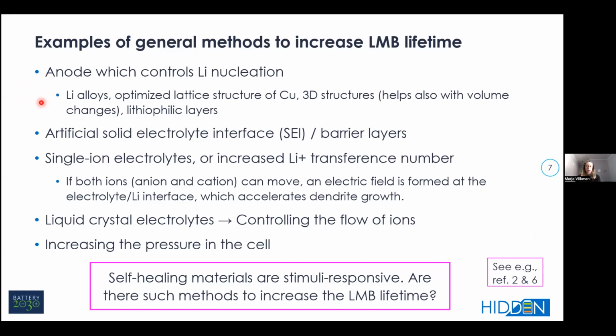So there can be different lithium alloys. We can also optimize the lattice structure of the copper current collector. Have some 3D structures in the anode or lithophilic layers, and these all help to have a smooth lithium nucleation on the anode, which will prevent the growth of dendrites. Then there can also be an artificial solid electrolyte interface between the lithium anode and the electrolyte, or a barrier layer. This will help to stabilize the lithium electrode.